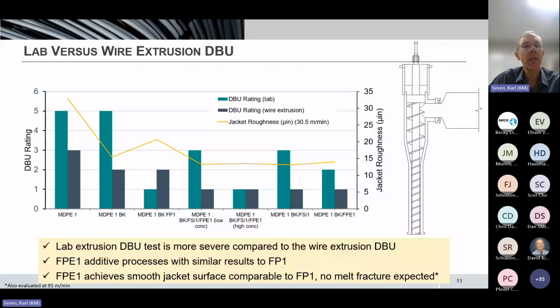The other thing that we saw was that this promising polar polymer additive showed similar results to the typical fluoropolymer-containing sample. And overall, these samples showed about equivalent jacket smoothness. So really no melt fracture issues would be expected with the modified sample with the polar polymer additive.